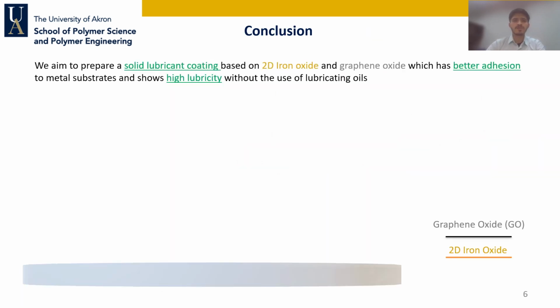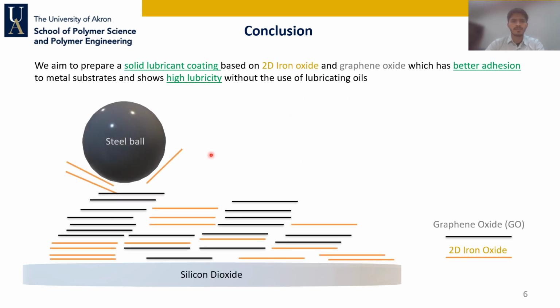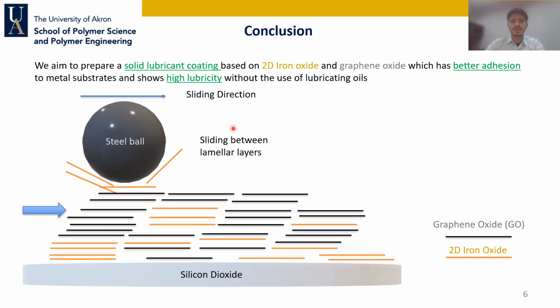So coming back to the hypothesis, I want to conclude by saying that we successfully prepared the solid lubricant coating, which has better adhesion, and it shows high lubricity without the use of lubricating oils. And the mechanism driving that is the low shear force in the lamellar structure of these 2D materials.